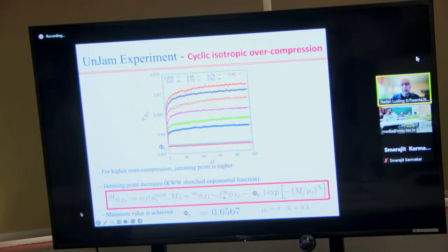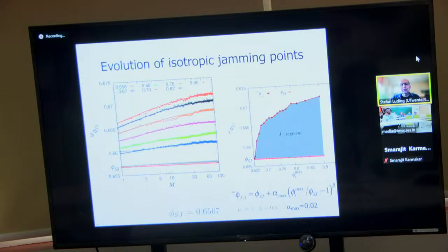You can go further. I don't want to go into details here, but this is logarithmic long-term aging. I only give you the keyword. This is the proof or the confirmation that the jamming density or the solidification density is a function of history. For different history, you get different densities in this gray area. So the consolidation density, the jamming density, however you call it, I do not call it yield density. The jamming density is a function of history. The yield density is another story. That's not the same thing.